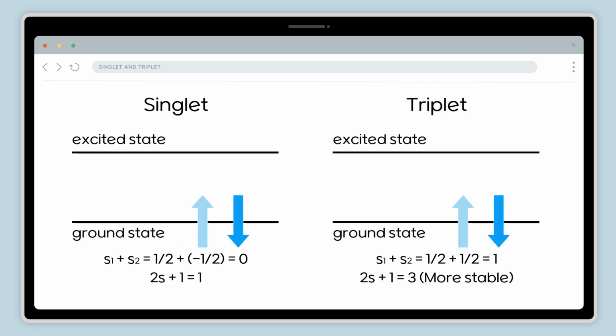Phosphorescence is developed to supplement the drawback of fluorescence, especially low internal quantum efficiency. To increase the internal quantum efficiency, phosphorescence uses the triplet exciton by intersystem crossing. Triplet is spin-forbidden but has slightly lower energy than singlet. Also, triplet has 3 times more available than singlet.